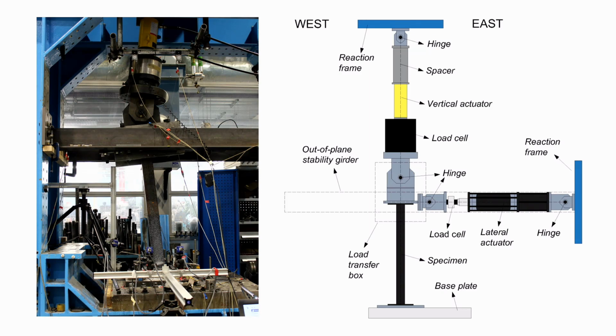And then for the test setup, we welded steel plates at the top and bottom of the specimen, and then we bolted the bottom plate to a very stiff foundation, so that the specimens were essentially tested as vertical cantilevers. And then we had a vertical actuator that applied the axial load, which was maintained throughout the test, and a lateral actuator that applied the lateral displacements.